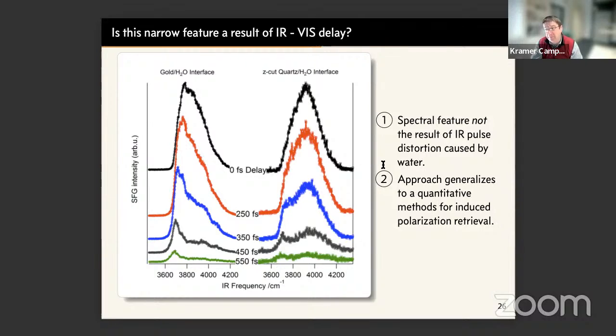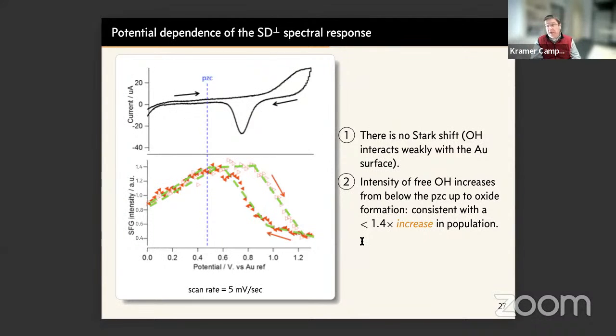as a function of delay between the two pulses, for the gold-water interface on the left, and for the quartz-water interface, in which no weakly hydrogen bonded interfacial OH is expected, on the right. You can see quite clearly that this strong feature at 3700 is largely absent on quartz. So all of this suggests to us that we can really see this single donor perpendicular species. Now you can do spectroscopy of this as a function of potential, because we're inside an electrochemical cell.